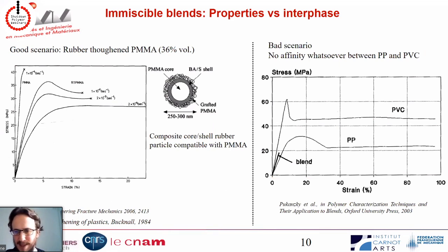So what is this compatibility doing to the mechanical properties? Let's start, for example, with what is on the right. On the right, you have two polymers, polypropylene and polyvinyl chloride. When you mix them together, you have this blend here, which has really bad properties. You lose all the elongation at break, and for the modulus, you have simply something that is in between the two initial moduli. Because there is no interface or a really small interface, no compatibility whatsoever, the properties of the blend are totally poor and the blend is useless.